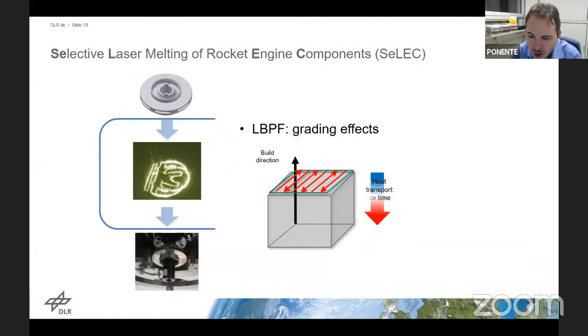So one maybe rather interesting detail is the grading effect that you generally get in SLM or LPBF, which is due to the directional cooling, because you have a directional physical process. You put in the laser energy from the top, you lower the build plate down towards the bottom with each layer, and the material is also towards the bottom, massive material, so the heat flux is going to be downwards towards the base plate. So it's directional cooling, and this kind of symmetry that you enforce on the physical process can lead, or should lead actually, to responses in the material.